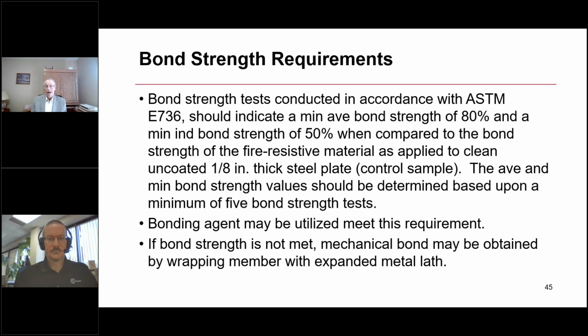Now, if you do not meet your bond strength requirements of 50% and 80%, then you can use a bonding agent to meet that requirement. If you meet the strength requirements with the bonding agent, then you're good to go. If it's not met, even with that bonding agent, then you need to provide a mechanical bond by wrapping the entire outside perimeter of the structural element with an expanded metal lath. And the guide information will give you more details on how to do that, the specifications on the metal lath, and so on and so forth.